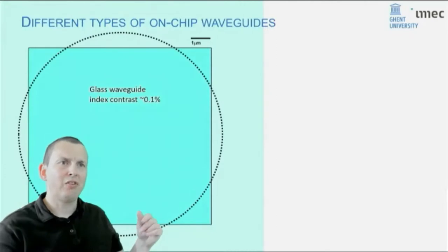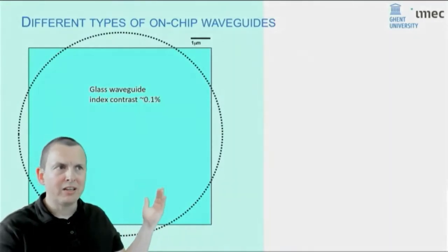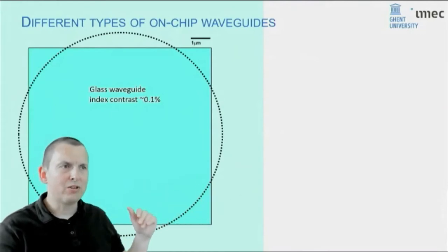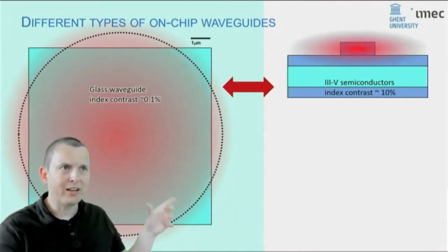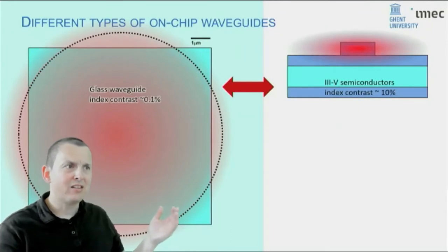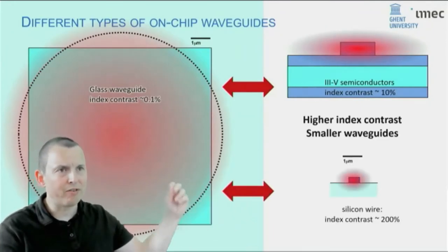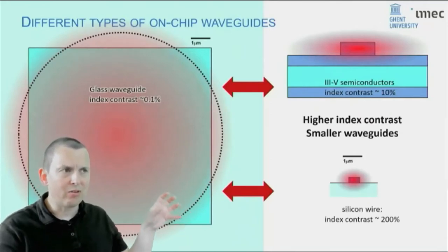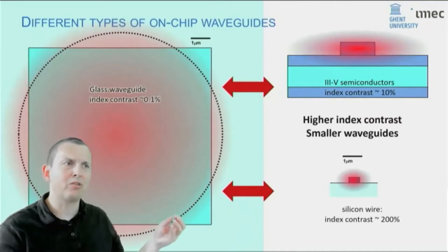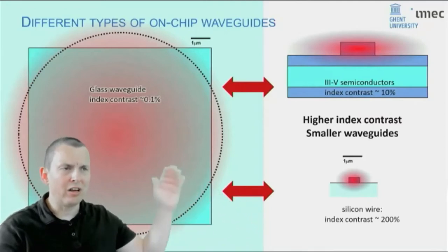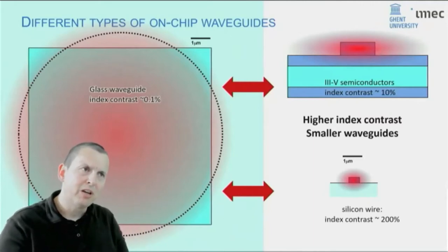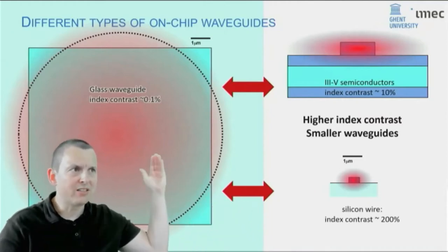The reason that sub-micrometer waveguides are possible in silicon is the choice of materials. Waveguides in glass, like optical fiber, have very low contrast between core and cladding, so the waveguide mode is very extended — typically about 10 microns. If you increase the index contrast, for instance in 3–5 semiconductors, you can shrink that mode to micrometer size. In silicon, which has a massive index contrast of 3.5 versus 1.5, you can confine your mode in an area that's like half a micrometer across. Because you have these very tiny waveguides, you can stack them close together and bend them very sharply, putting lots of them on a chip — many more components on the same footprint than in glass or 3–5 semiconductor technology.